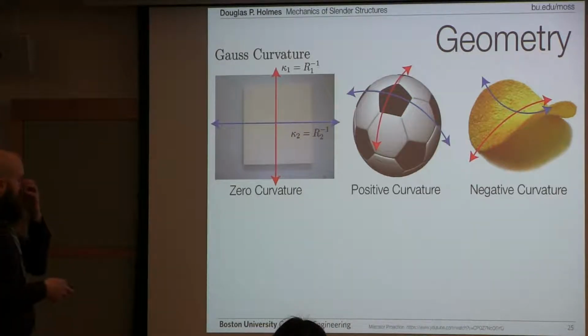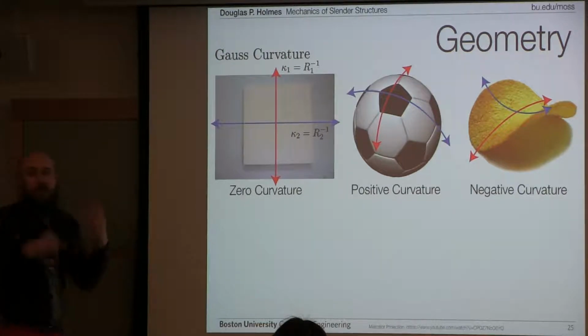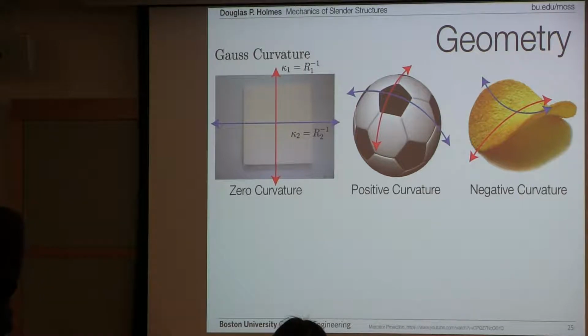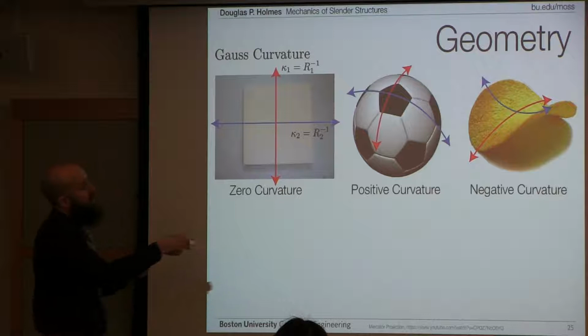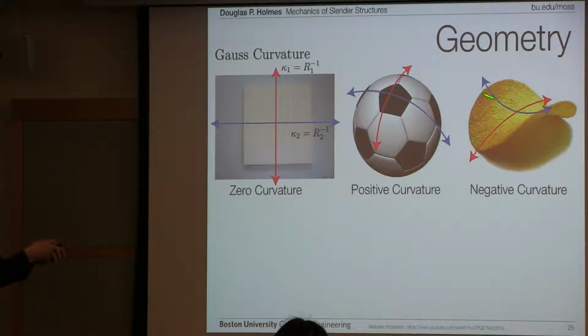The reason why geometry messes things up is because you can look at something called the Gaussian curvature of an object. The Gaussian curvature is, in the simplest terms, the product of the two principal curvatures of this surface. So for a sheet of paper, it's this curvature in this direction multiplied by this curvature. This thing's flat, it's just 0. For a soccer ball, you get positive curvature here, positive curvature here. The product of those two positive numbers is a positive number, and so you get a positive Gaussian curvature. And similarly, for something like a Pringle or a saddle, you get one curvature in one direction, one in the other, so you have a negative curvature.